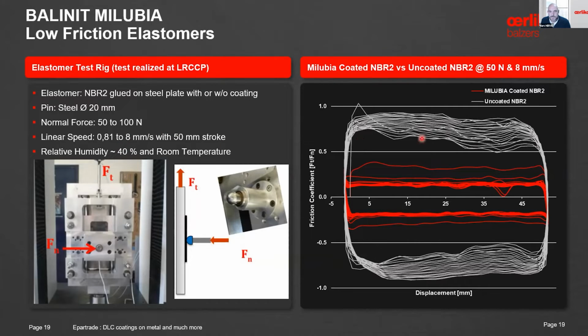what we saw immediately, so the gray part is the pin that you see here against the uncoated elastomer. You can see that the friction is definitely not great, I would say. It's still really high. And we were actually very surprised to see that as soon as we applied the sample with the Milubia coating on it, we dramatically reduced the friction. So, that was our first lesson. Okay, friction can be reduced.